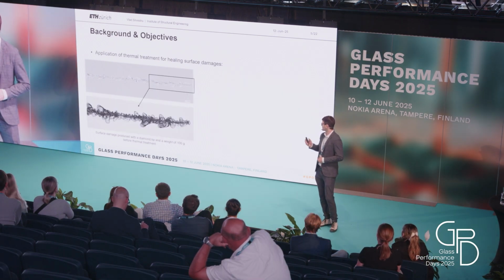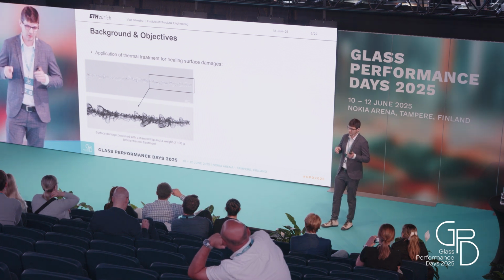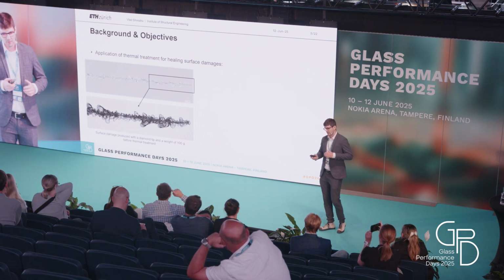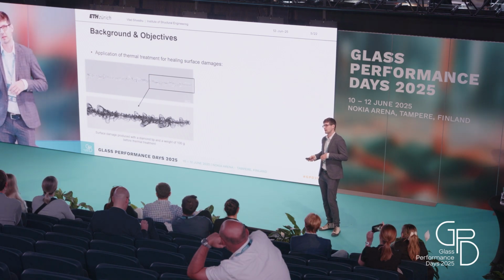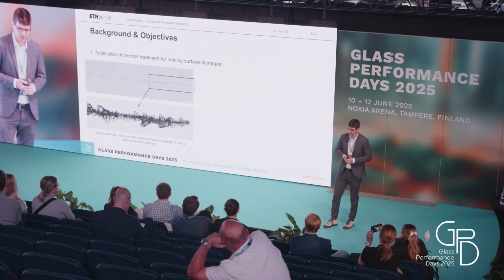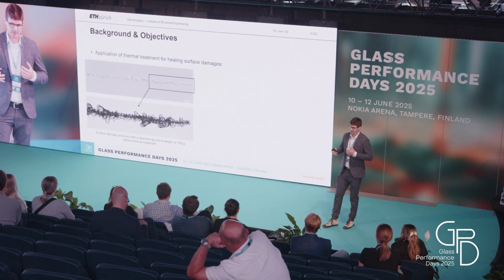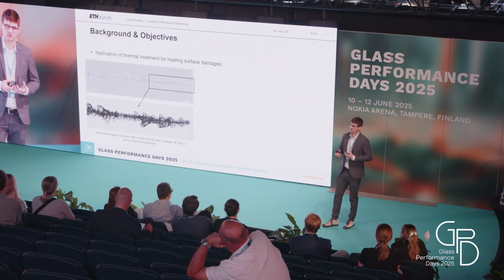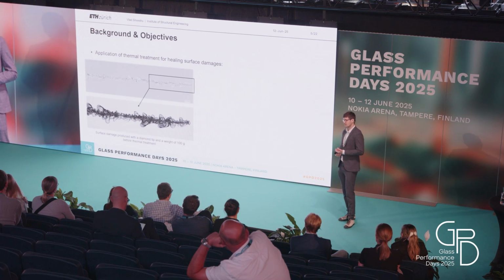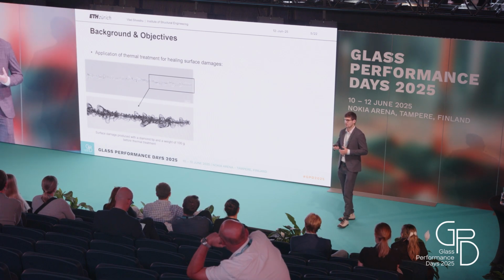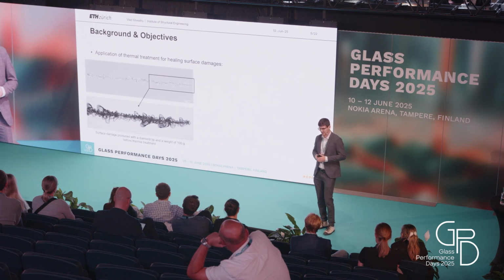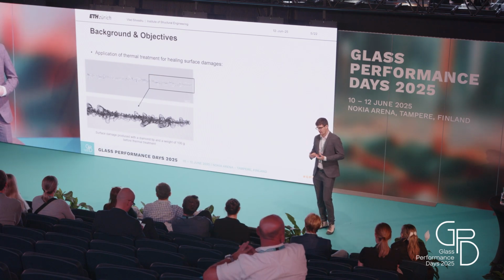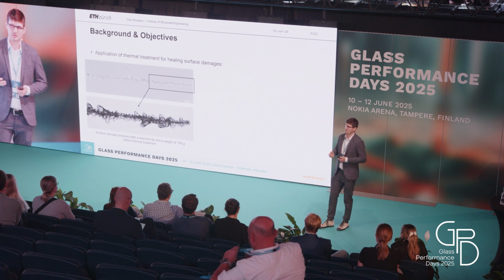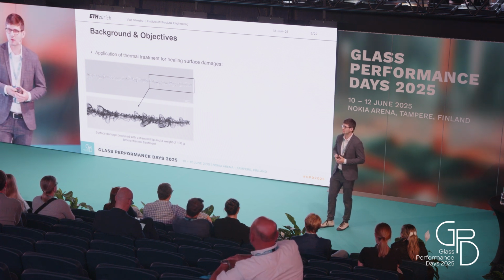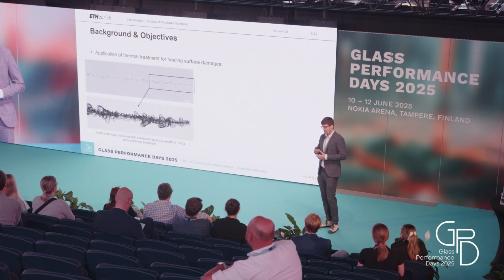For the first topic, I will not focus a lot on it, but we also saw yesterday in the presentations that by applying different temperatures, we can heal to a certain extent the scratches. However, there are two aspects. One is increasing the strength of the glass that is scratched. The other one is the visual appearance, as the scratches might also disturb the aesthetics. Increasing the strength is already possible to a certain percentage with lower temperatures. But we saw also yesterday that the visible scratch might still be on the glass.